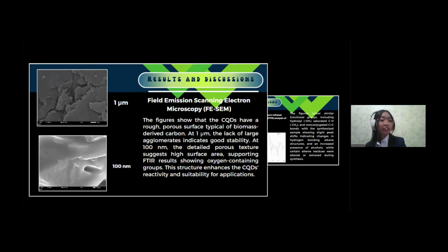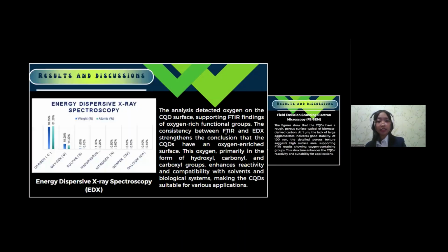Next, we have the energy dispersive X-ray spectroscopy, or EDX, results, which confirm the presence of oxygen on the CQDs' surface. This also supports the FTIR findings of oxygen-rich functional groups. While FTIR identifies functional groups by their vibrations, EDX directly measures the elements present. Together, these results confirm that the CQDs have an oxygen-rich surface, mainly from groups like hydroxyl, carbonyl, and carboxyl. This oxygen content helps improve the CQDs' reactivity and makes them more compatible with different solvents and biological systems.